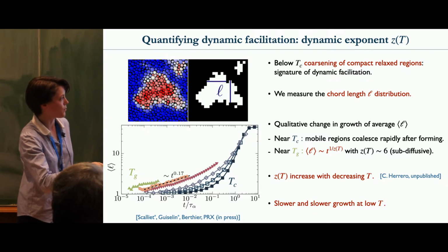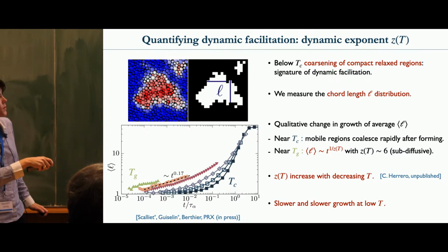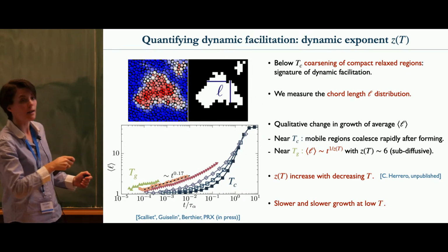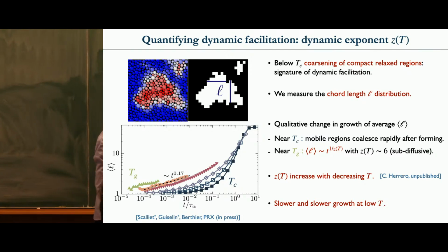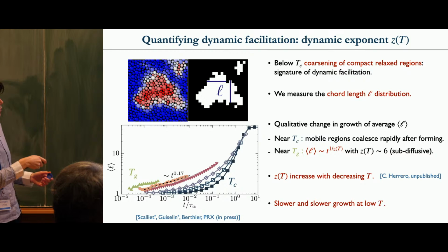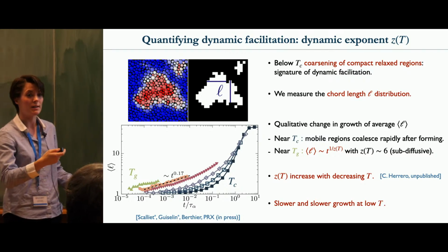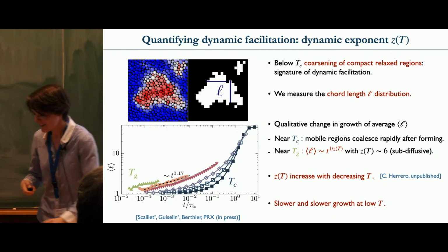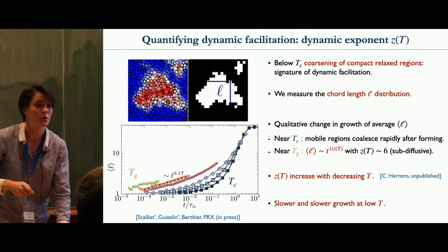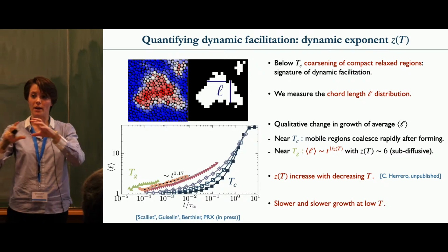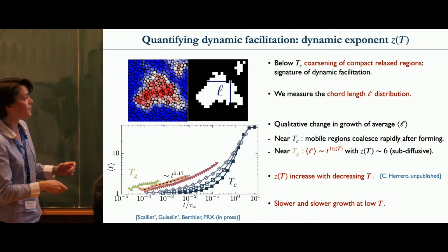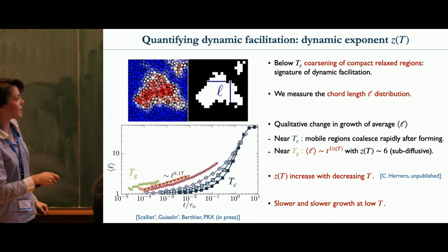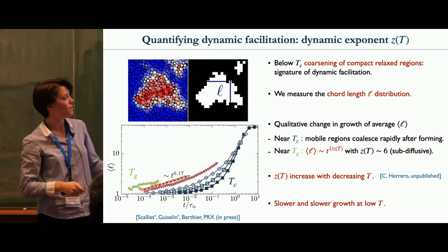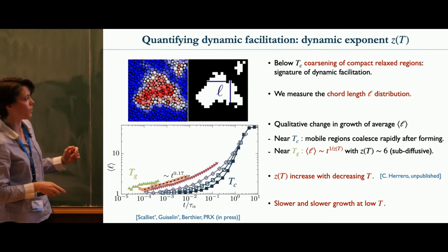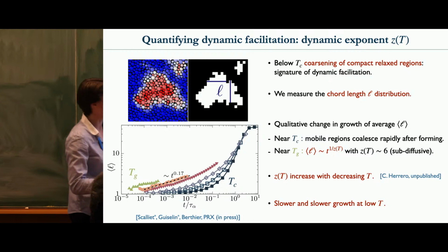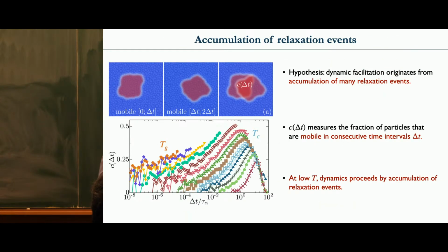So we have this relation in which we introduce a dynamic exponent which relates time and length of these dynamic heterogeneities. And the fact that we can measure this is highly informative, because what you see here is that this dynamic exponent is huge. It's 6. So this means that the dynamics is highly subdiffusive. These regions start to pop up, and then they grow, and their growth is extremely slow, and we can directly quantify it. In these data, you can see that this exponent changes with temperature, and this is being measured independently by Cecilia Herrero in Montpellier. And the growth is slower and slower at low temperature.